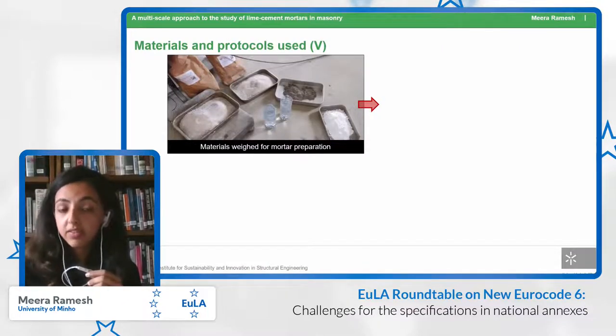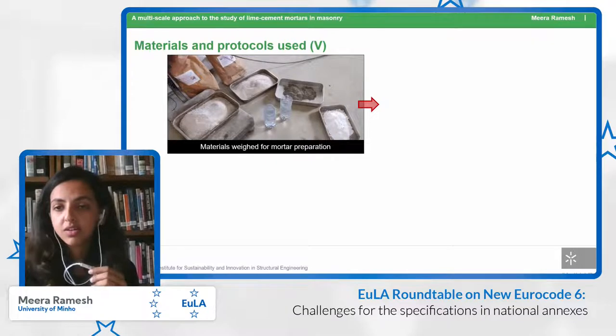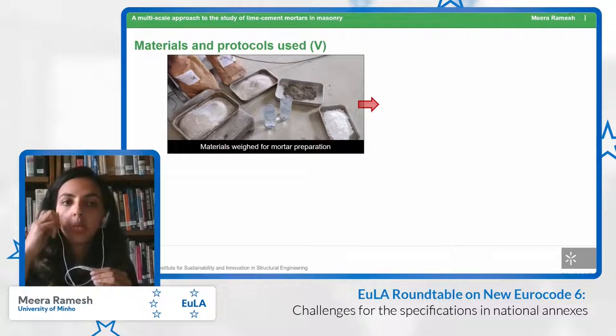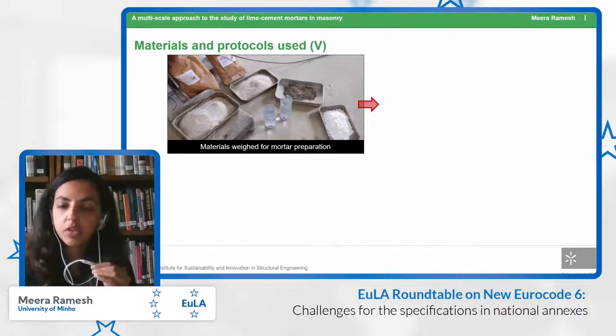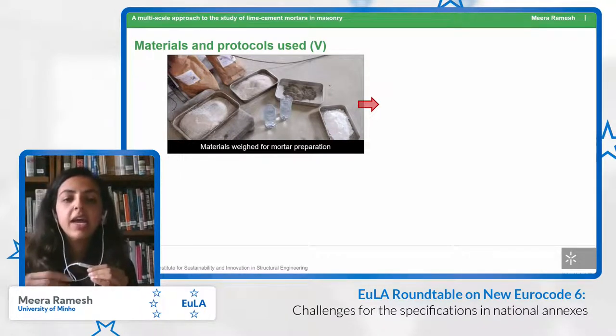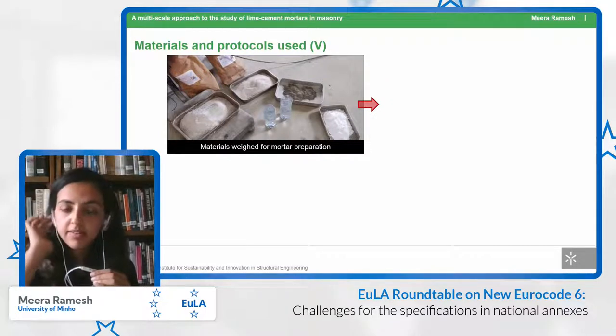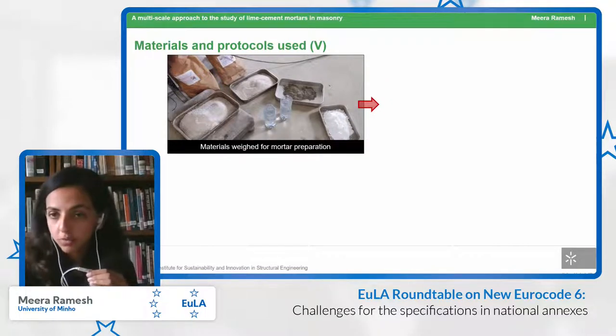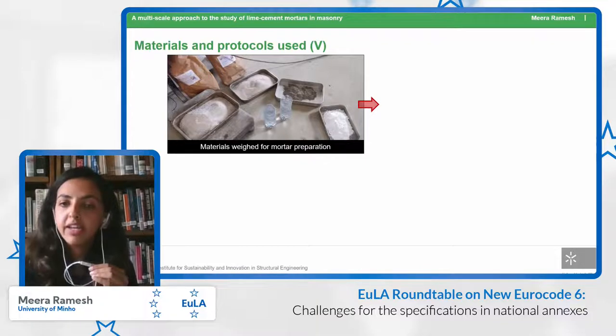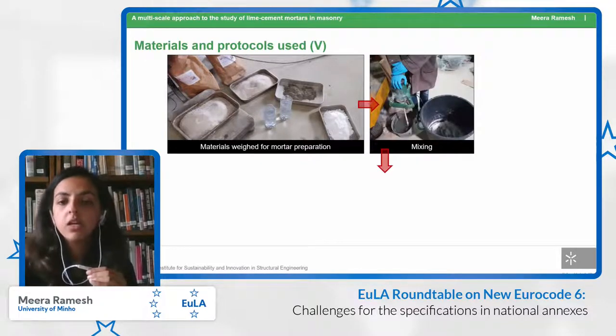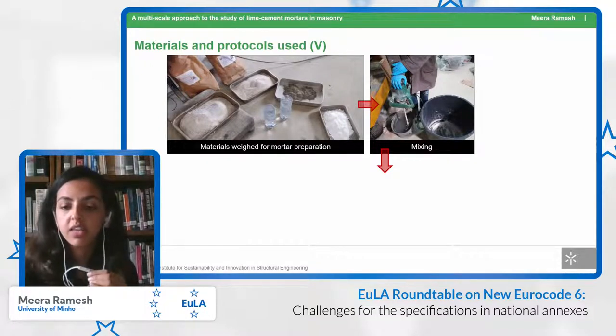For masonry level studies, we had to construct specimens and so therefore the mortar casting had to be done at a much larger scale. So we had batches of around 12 to 13 kilos of aggregate and we weighed all the materials. Of course, the mixes were by volume, but in every casting, we converted them to weight using bulk density. The mixing was done using exactly the same protocol, just in a larger scale.